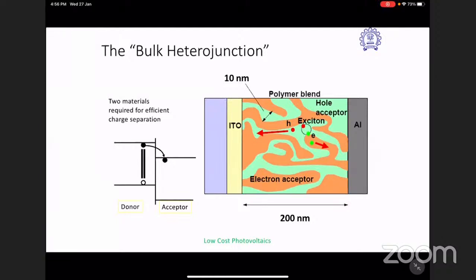That is fine. So we could separate the charges, but we also have to bring them out of the device. In order to bring them out of the device, we need to have continuous pathways. So we need to have the green connected all the way till the ITO and orange connected all the way till the aluminum. And so a kind of interpenetrating network is required. Further, the exciton cannot diffuse more than 10 nanometers. That is mentioned by this arrow. So you have to have this semiconductor mixed in the bulk form, not in the bilayer.